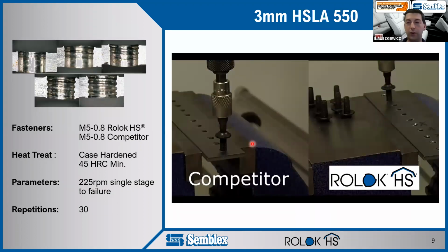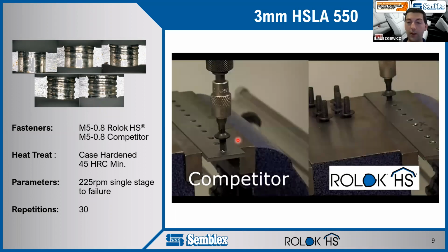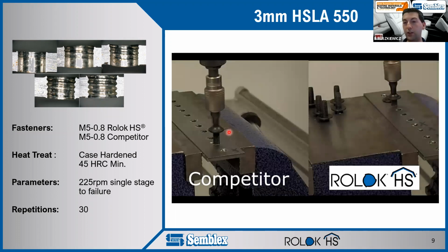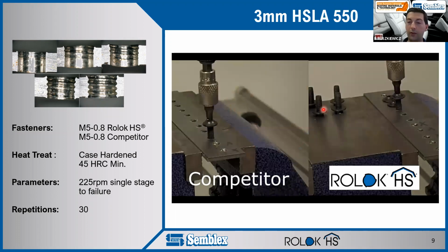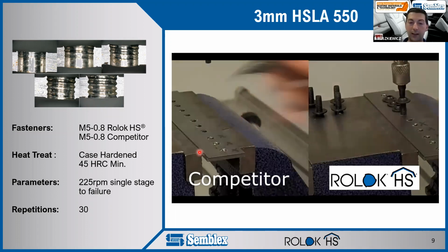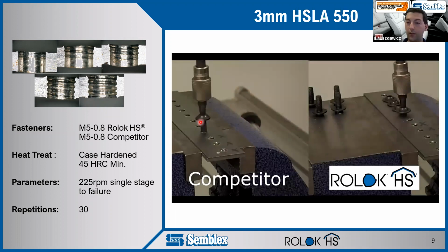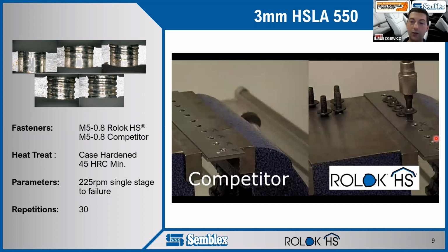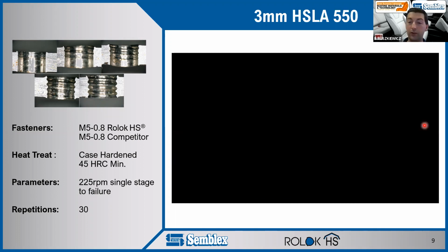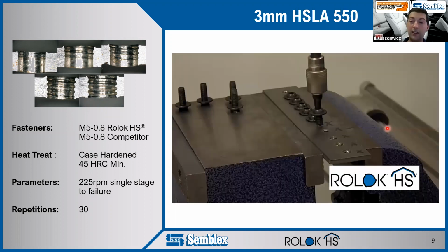So going back to this original customer problem where the traditional thread rolling fastener wasn't working, and what we originally tried to solve with Rolok HS, we can see that on the left we have that same video you saw earlier, but on the right we're now driving Rolok HS in, and it's actually the same plate. If you notice these X's that I keep drawing on here, if you look over to the right screen, you'll see those same X's, and we'll actually take Rolok HS and drive it straight through those same holes to show that it's the same plate.